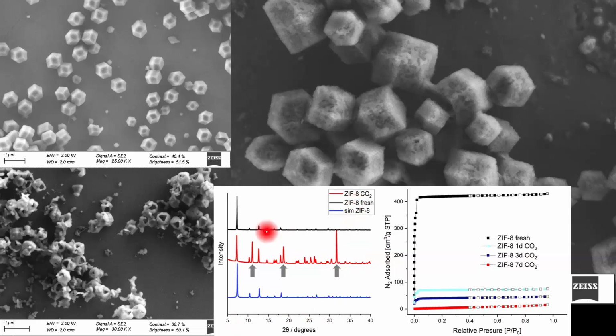So you go from this simulation when you synthesize it, and suddenly when you put it in the CO2, you have a new phase that is not porous. And that's the reason, because this is BET, the adsorption of nitrogen of the original MOF. After 1 day, 3 days, and 7 days in the incubator, it decreases completely because you are getting a new material. It's something that I want to publish because people are still publishing drug release with ZIF-8. A lot of papers every day. And it doesn't make sense. If something that you put in the cell culture immediately falls apart like sugar, you can actually put the drug directly. It doesn't make any sense.